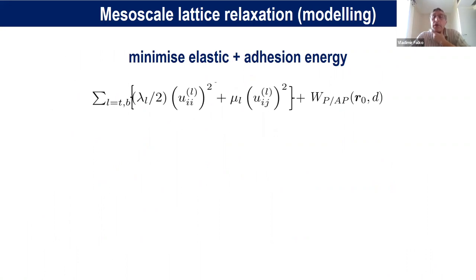So the local calculation we did in the DFT allows us to describe the dependence of adhesion energy on the local stacking. And this energy of adhesion is the reason for the layers to adjust their lattice constant or the atomic positions to each other from the initial one to the energetically more preferential.